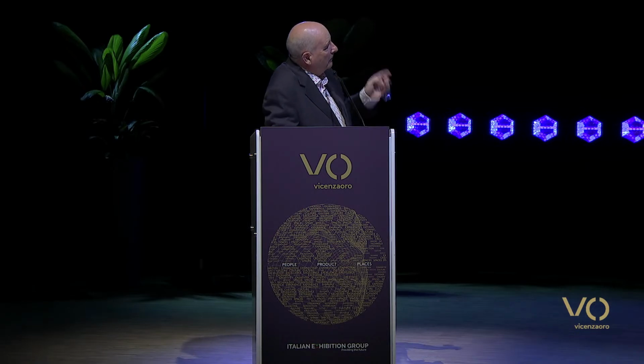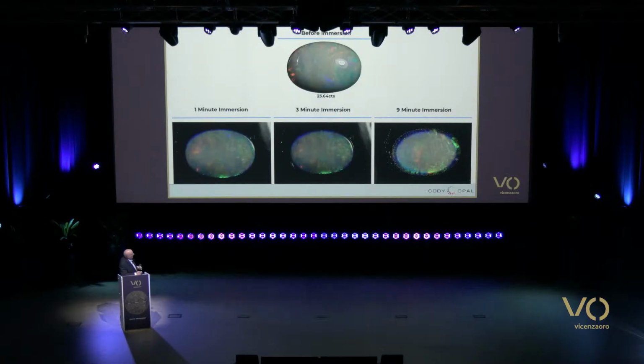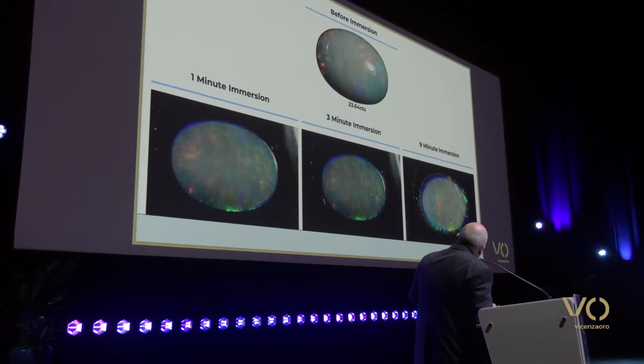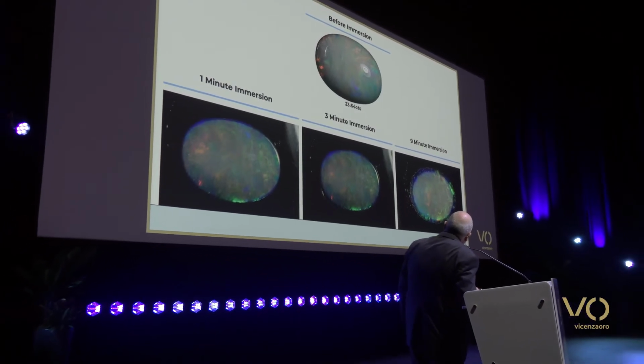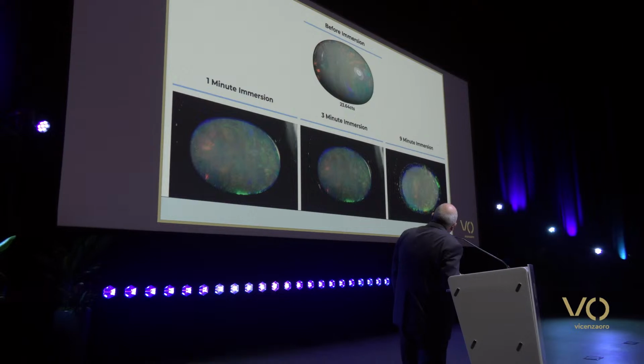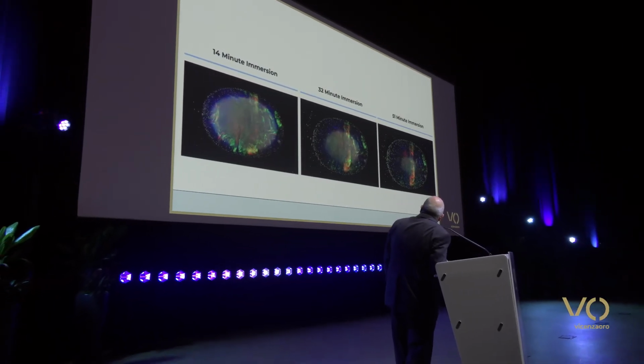So poor old consumers. This is a test we did. We started out with a 23.6 Ethiopian opal, and you can see what happens. You can see the little bubbles appearing after 9 minutes. And by the time the 51 minutes are up, you can see bubbles appearing everywhere. And it was like champagne, bubbles coming off this stone.